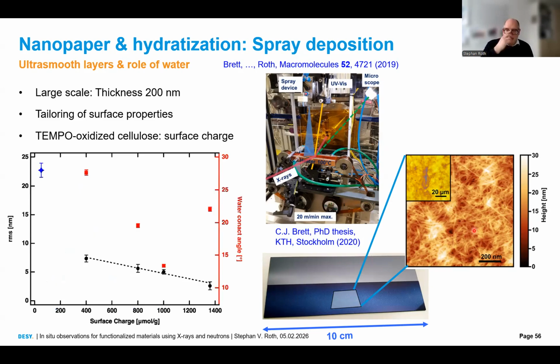So first thing you do is you take a droplet of water and you measure the water contact angle. Remember what I said, we can put a surface charge on these fibrils. Bacterial cellulose here in blue is basically without surface charge. And you see when we spray it, we get a rather high roughness, 20 nanometer. When we use charged cellulose with carboxylic groups, you see that we can reduce the surface roughness down to 2.5 nanometer.